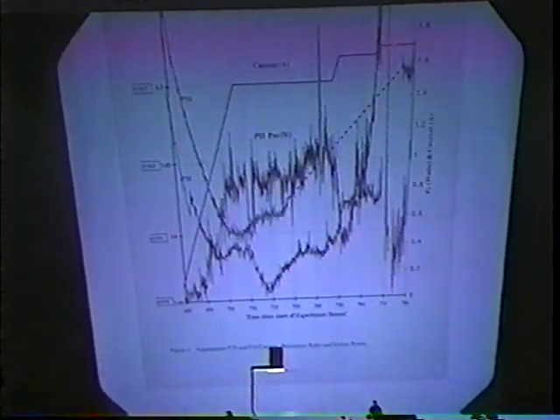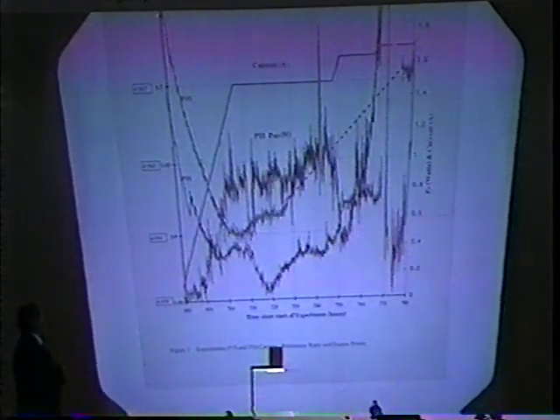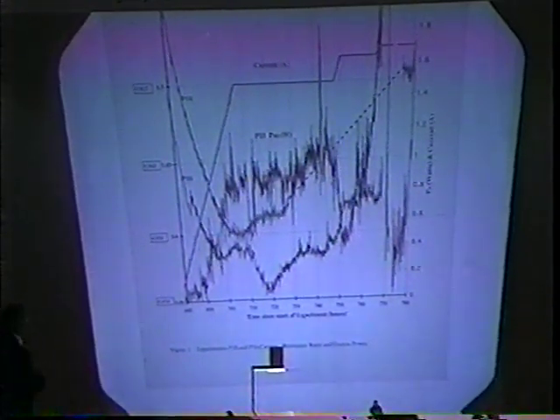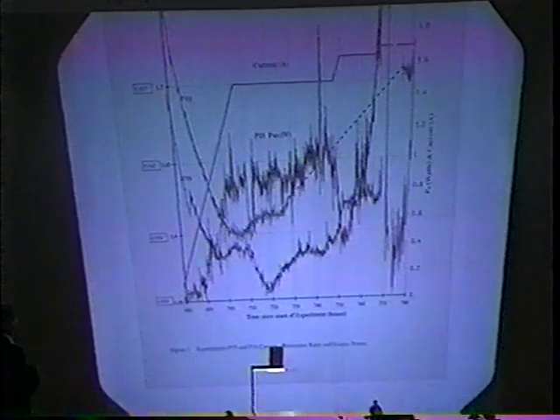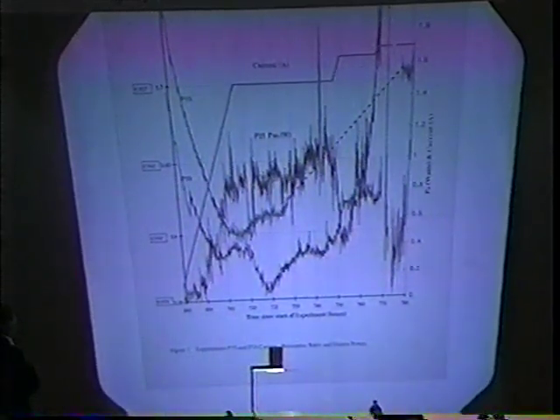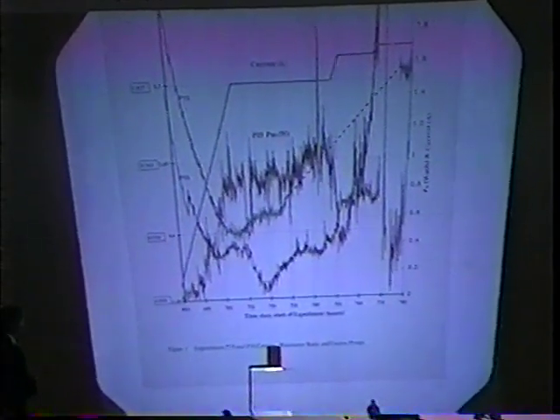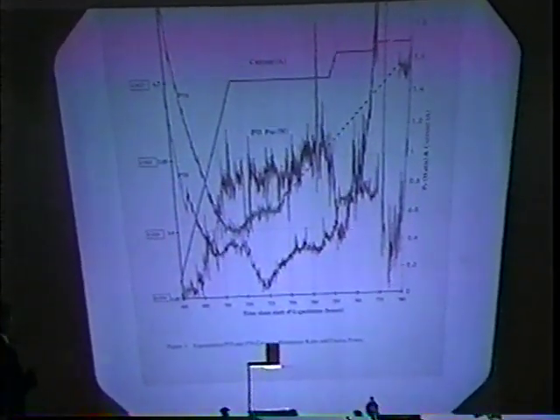So we're looking at loading, according to our early calibration of the resistance ratio versus loading functionality. This P16 was loaded to something like 0.91. As we started up a current ramp, the loading increased. At some point, a very high current, 1.5 amps, 500 milliamps per square centimeter,